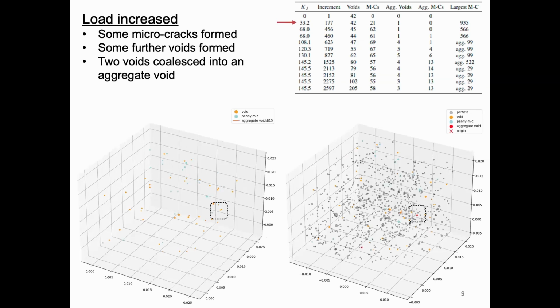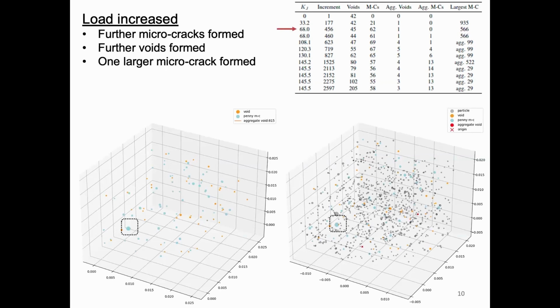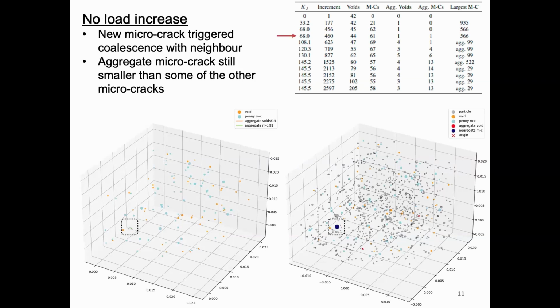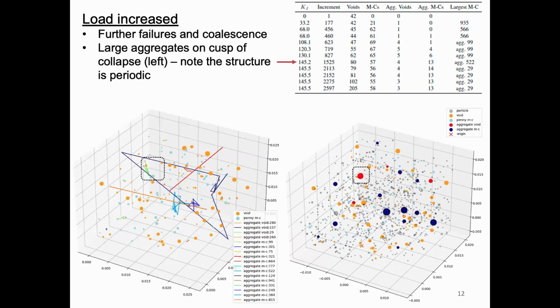So when you start increasing the load, you see the first penny-shaped cracks forming. These are the blue dots here. And some voids are increasing, and the first aggregate of two voids. You increase the load further, and you see further microcracks forming or extending, and a large microcrack over here. At the same load, in the next simulation step, this microcrack consumes a neighboring void. You can see here from the reduction of the voids, and it becomes a larger microcrack. And this is going on. These lines here show large defects. The reason they are lines like that is because this is a periodic structure, so this point is actually very close to this point on the other side. So it's a little bit confusing.